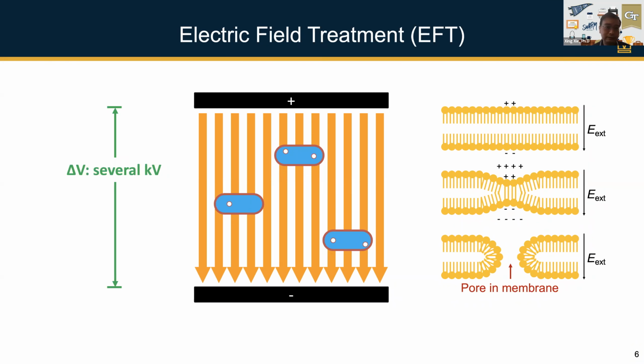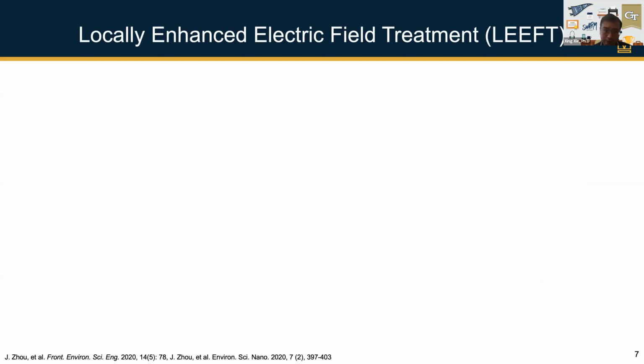So that's why we came up with this idea. Instead of generating a uniform electric field between two parallel flat electrodes, we try to create a locally enhanced electric field. By doing that, we only use a very small voltage, and with the enhancement effect, we can achieve an electric field strength locally in the system that's strong enough to realize bacterial inactivation.